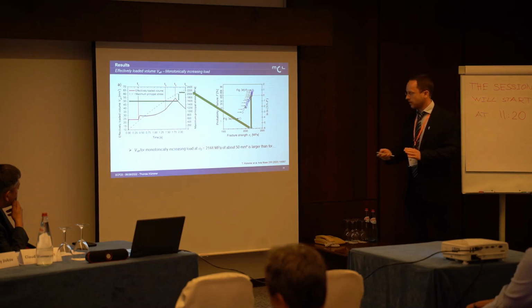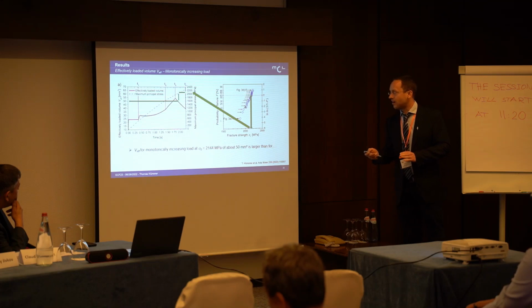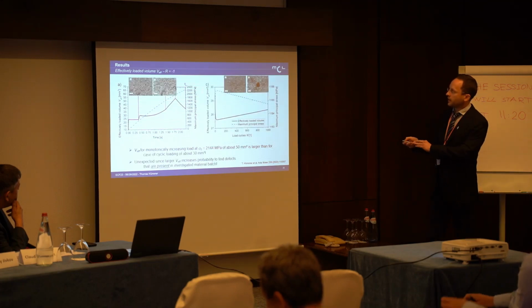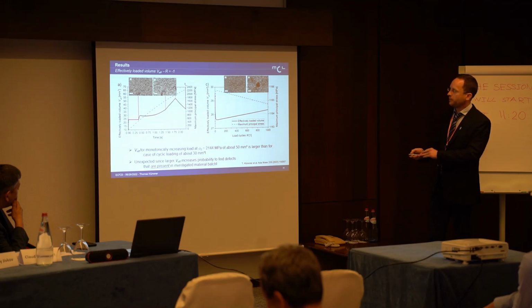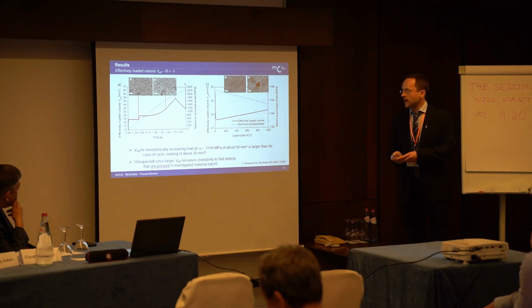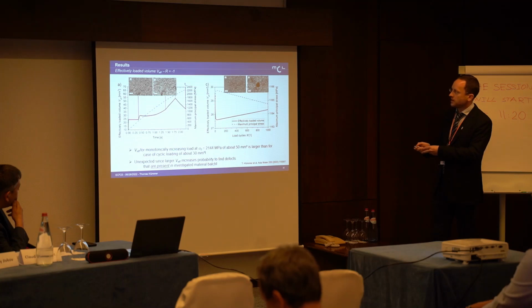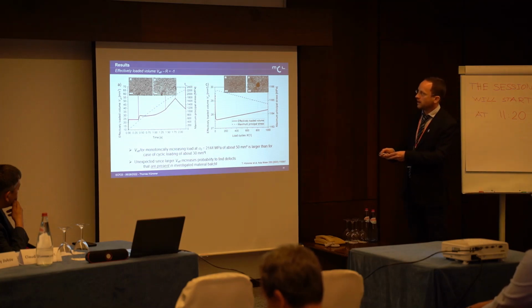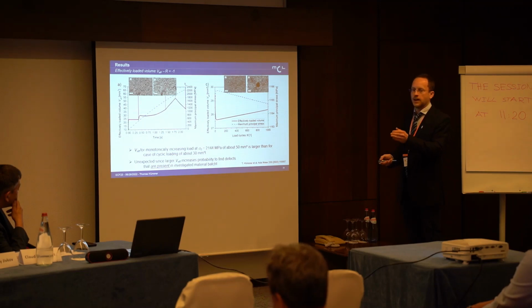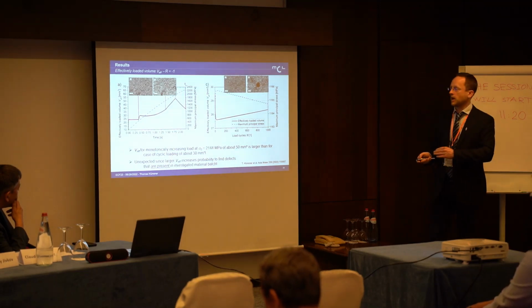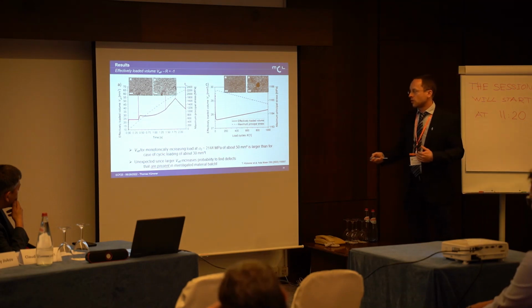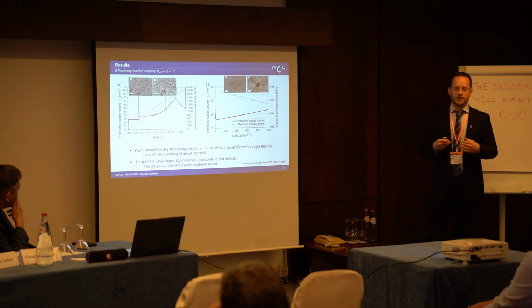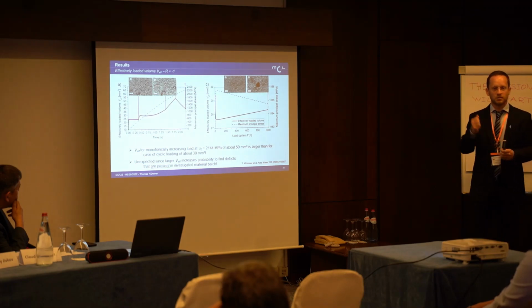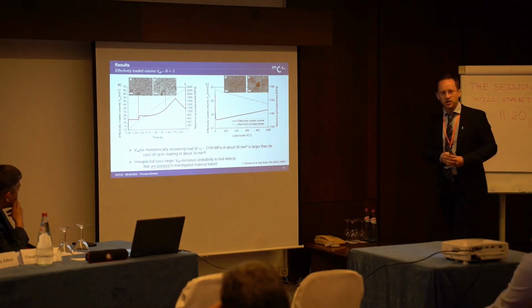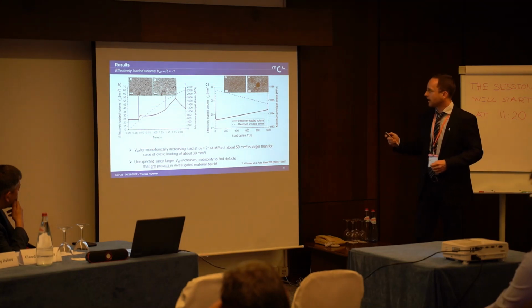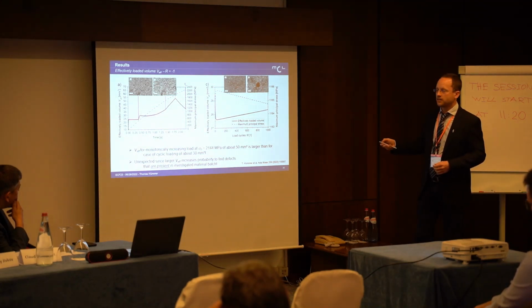And this 50 cubic millimeters is a value larger than for the case of R-1 loading, where you have less plastification and also therefore less effectively loaded volume. It stays in that region. Remember, I told you before, it rises from this region here, and the case of R-1 loading, due to the lower stress amplitude, stays in this region. So one would assume that this lower effectively loaded volume would be a smaller net, so to say, in which I catch fish in the fish pond, and I should find those defects that I showed you earlier in the bigger effectively loaded volume.